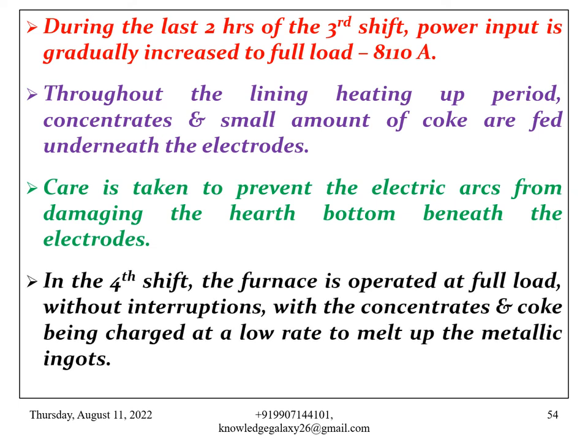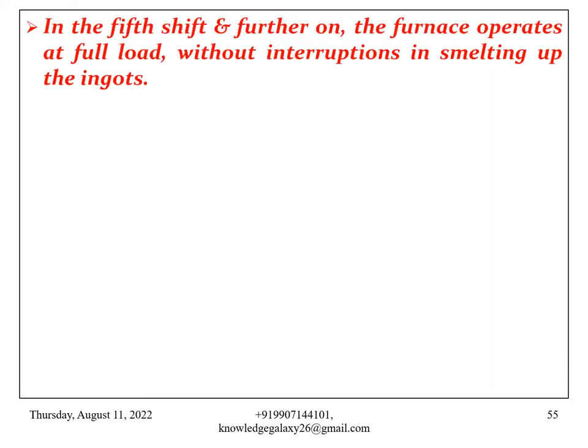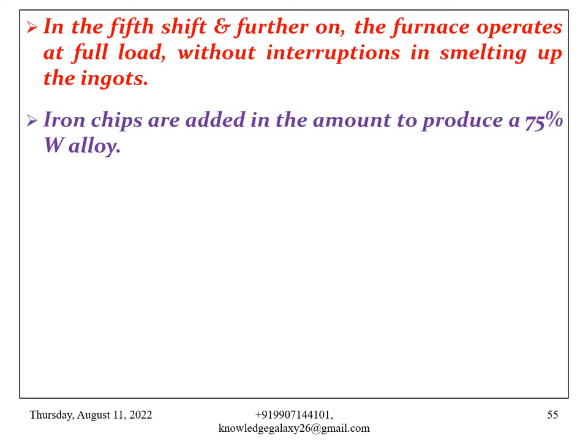In the fourth shift, the furnace is operated at full load without interruptions, with the concentrates and coke being charged at a low rate to melt up the metallic ingots. In the fifth shift and further on, the furnace operates at full load without interruptions in smelting up the ingots. Iron chips are added in the amount to produce a 75% tungsten alloy.